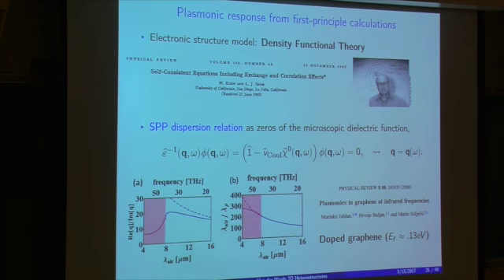So how do we compute or predict this kind of properties? Usually we have to go to a very detailed description of the system. So this is done looking at density functional theory simulations, for example. And we can look at these plasmons at resonances of the electrons as we impose electrical fields. So we have to look at the microscopic dielectric function, which is this operator, epsilon minus 1, depending on a given wavelength and the wave number. So as we impose a total field, we want to know what is the applied field that we have to give for this total field to appear. So this is the result of this computation over here.